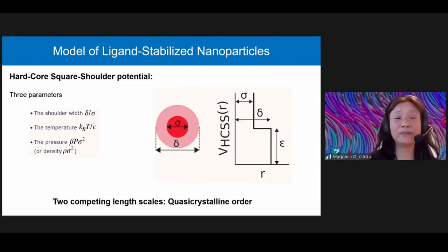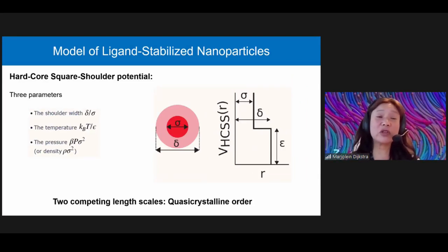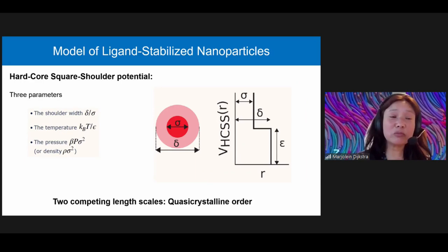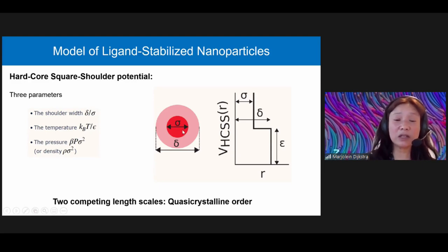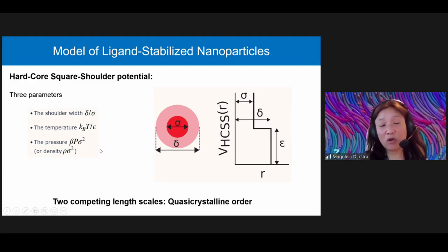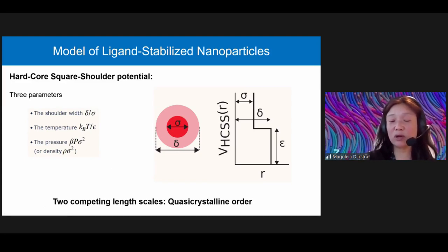the particles are. So for that, we use a very simple model of ligand stabilized nanoparticles. It is a hardcore square shoulder potential. The nanoparticle is mimicked by just a hard sphere with a diameter sigma, and then the ligand layer is mimicked by a square shoulder potential with a shoulder width of delta. The design parameters are the delta, the temperature, or the pressure, or the density. And because there are two competing length scales, it gives rise to quasi-crystalline order.